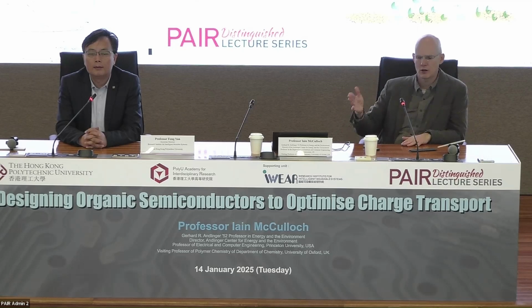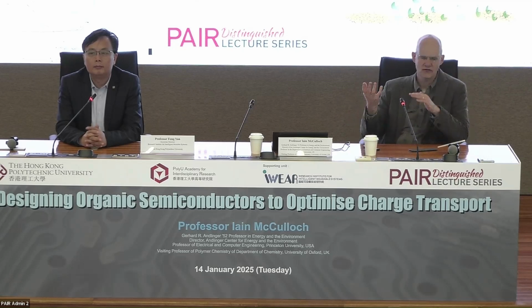The cross-linking only plays a role if you're worried about sequential deposition from solution, and whether the solvent is going to dissolve the layer below.